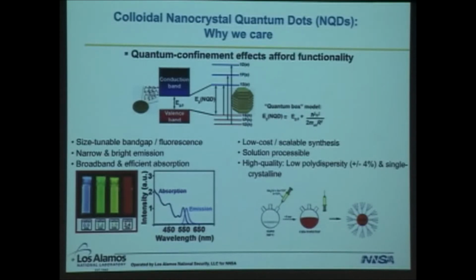And despite the fact that we're using sort of low-tech methodologies to create these materials, we get a high-quality product out. The nanocrystals are single crystalline, and they exhibit low polydispersity when done correctly, on the order of plus or minus 4%, and that allows us to achieve these very narrow emission bands. And typically for cadmium selenide, for example, the full width half max is between 20 and 25 nanometers as prepared right out of the flask.